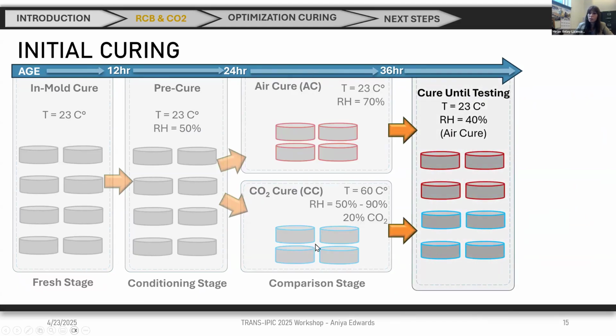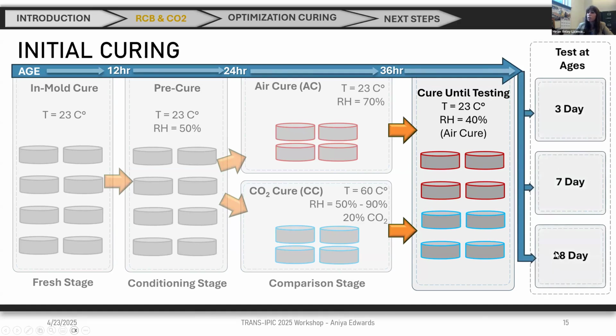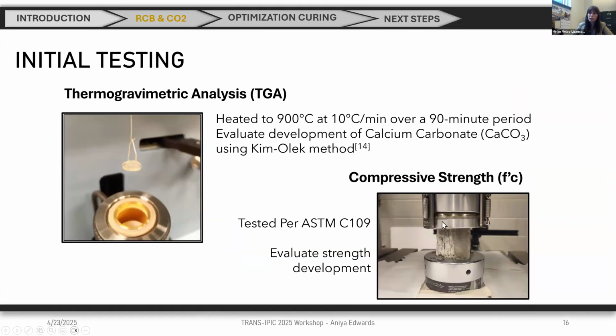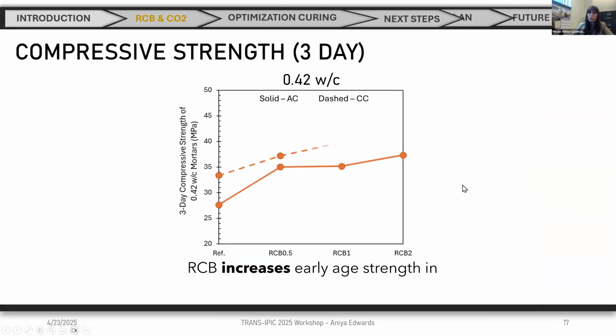And this is just for a period of 12 hours, and for the rest of the time until testing, they are kept in exactly the same condition. So the only difference is here. And then we will test at 3, 7, and 28 days. We did the TGA, and also we did compressive strength tests, among others.